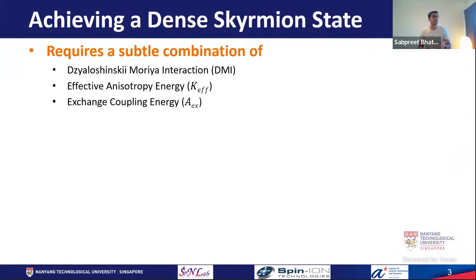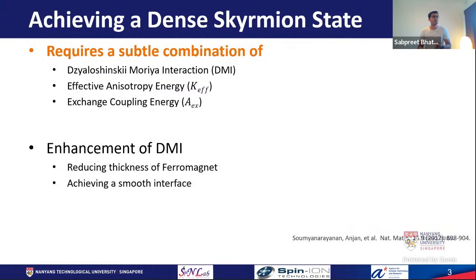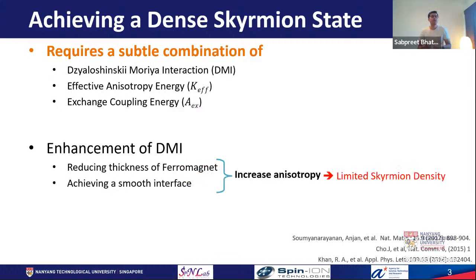However, to achieve a highly dense skyrmion state, one requires a subtle combination of magnetic properties, especially the ratio of DMI over the product of effective anisotropy energy and exchange coupling energy has to be higher. The ways by which a DMI can be increased involves reducing the thickness of the ferromagnet, achieving a smooth interface. But this also results in increasing the anisotropy, which limits the skyrmion density.